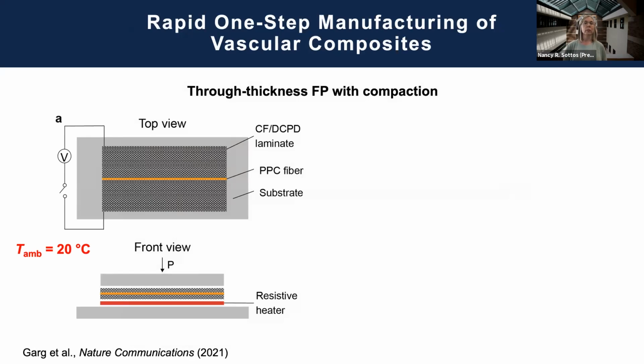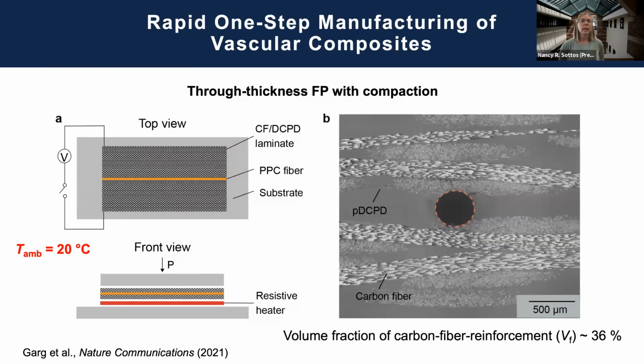What I'd like to finish with, though, is that we've been able to extend this process from the pure polymer to the composite. And so we're able to do this rapid, essentially one-step or tandem manufacturing of vascular composites. So we put basically our PPC fiber in. Again, we're going to rely on the through thickness cure to evacuate these in a composite. And we're quite successful, even though the reaction temperatures in the composite are somewhat lower than in the neat resin, the maximum front temperature. But you can see that we've fully evacuated a vascular channel in this woven composite.